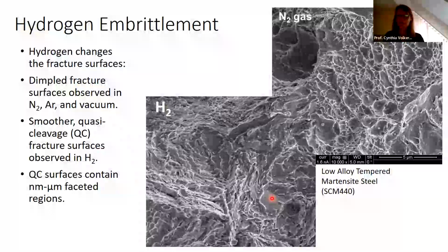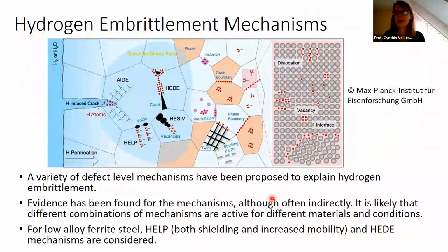And then when one tries to understand what the mechanisms are that lie behind it, what one ends up concluding is that the embrittlement is controlled by the defects in the material and the fact that hydrogen interacts strongly with those defects. So that's the basic idea, and I think everybody agrees at that point. But after that point, which defect interactions with hydrogen are relevant and controlling, there's a lot of discussion, a lot of different opinions, and probably that's because for every material and under different conditions, there are probably different combinations of mechanisms that are controlling.